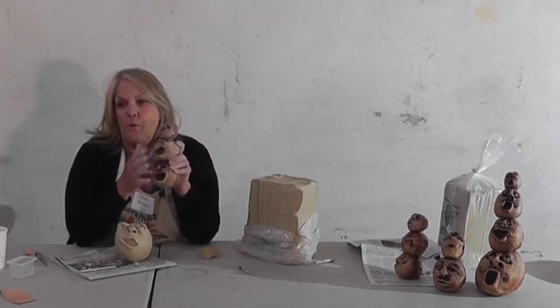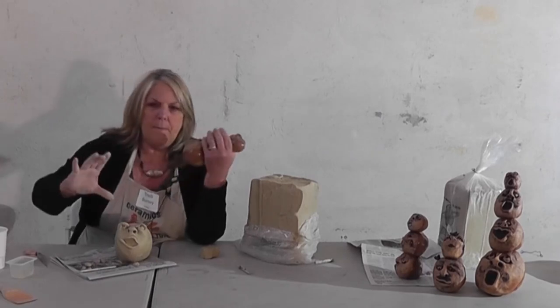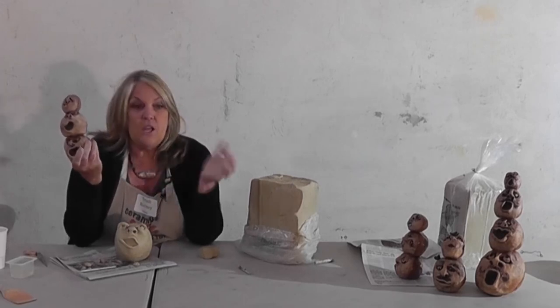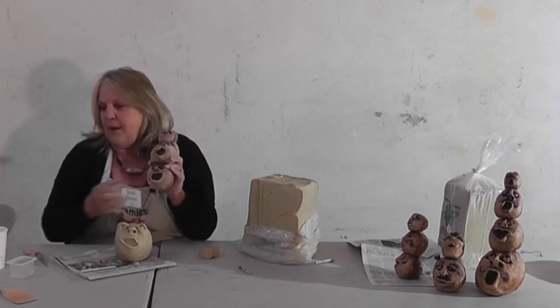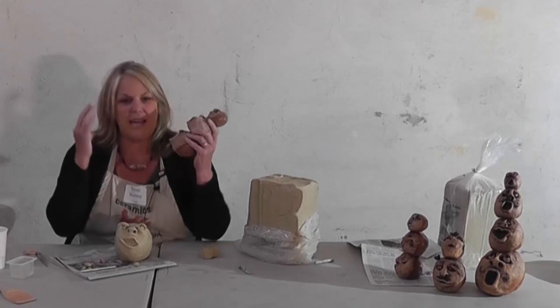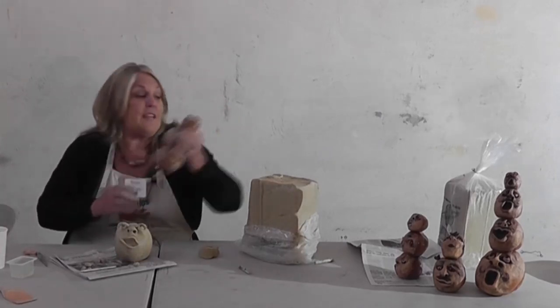What I found best for the faces is not to glaze them, but just to use a pure oxide wash. If you've never used them — you buy a bottle from Matt over here at Clay Planet. I like the iron and manganese — that's what these are. You dilute it and rub it on, so it looks completely black. You'll think I'm crazy — then you take a sponge and wipe it off, and you get all this great expression, the nooks and crannies, all this great color. He'll look kind of flat now, but once they have the oxide wash on them and they're fired again, they come up with all this greatness. So that's how you finish it.